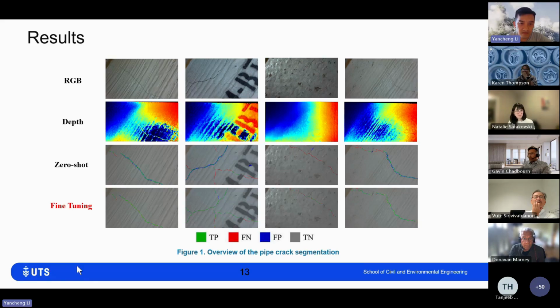But you can see the color difference on the labels on the crack. The green one is true positive, so if all the cracks are green, like this one, it is perfect. Then we have false negatives. The thing you don't really want is a false positive. So as you can see from the zero-shot, we have a certain level of success in labeling and quantifying the crack. Maybe it somewhat exaggerates the crack width here, which is not something we want.